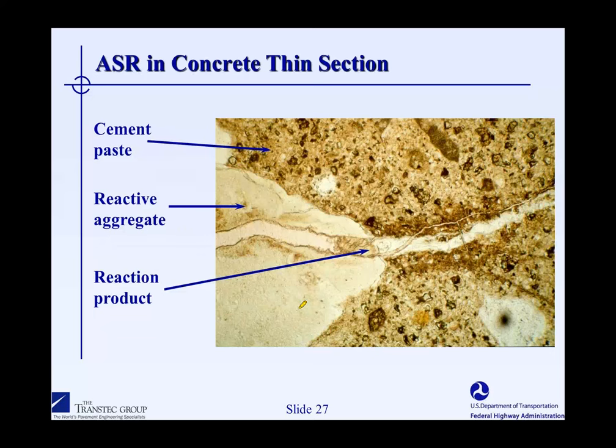This is what ASR can look like in a concrete thin section. This is a microscopic section cut from a piece of concrete. It's polished so thin that it will actually transmit light. It's under high magnification. The width of view here is about 1 millimeter or 40 thousandths of an inch. The grain you can see to the left is a small sand grain, a grain of flint aggregate. It's a reactive aggregate. And the brown material is the cement paste on the right-hand side, top and bottom.